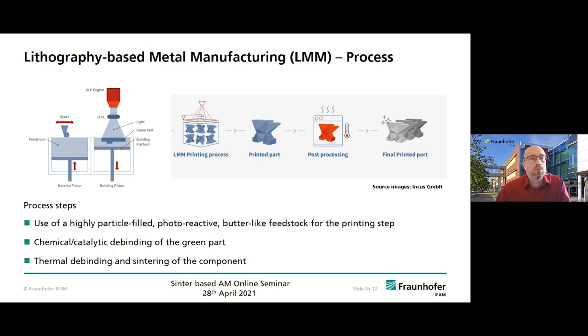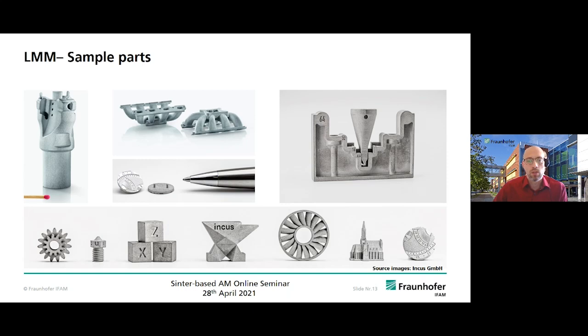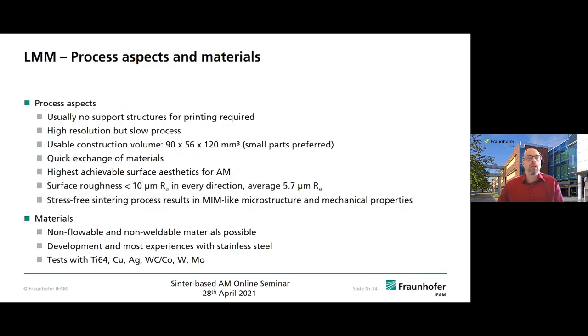So it's the same process as DLP printing from this perspective. And then you can lower the platform and add the next layer and thus build up your parts, as you can see on the right side, making printed parts, and then have basically the same post-processing by debinding and sintering. You can see some examples. Thanks to Incus, we have some very nice pictures of these parts that you can see here. And it's really a very precise method, with very high resolution, because you use the light as a source for hardening your material. And this makes it very interesting for very small parts, mainly.